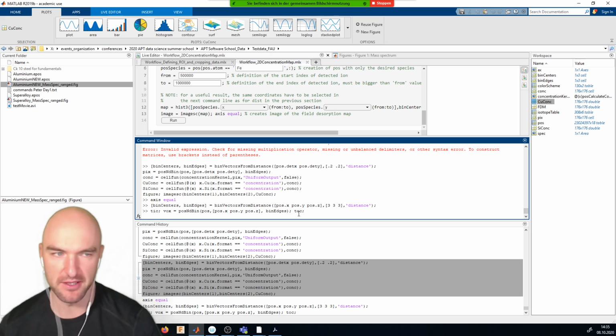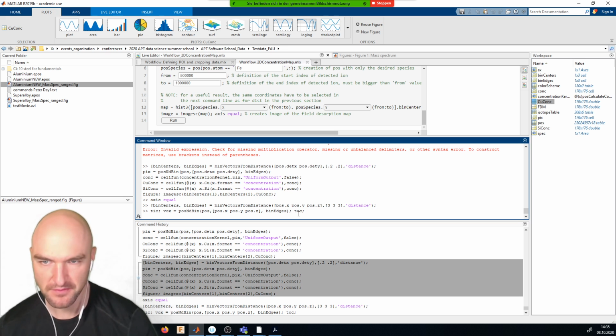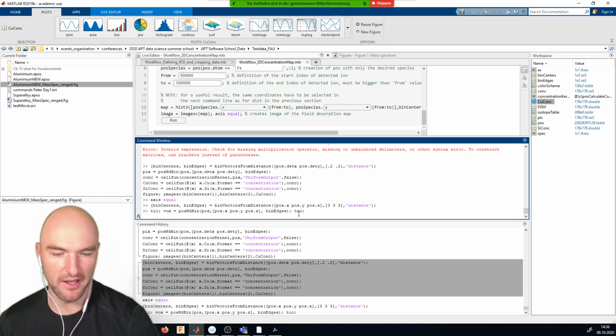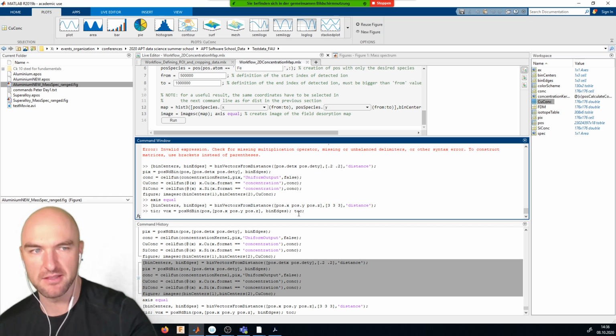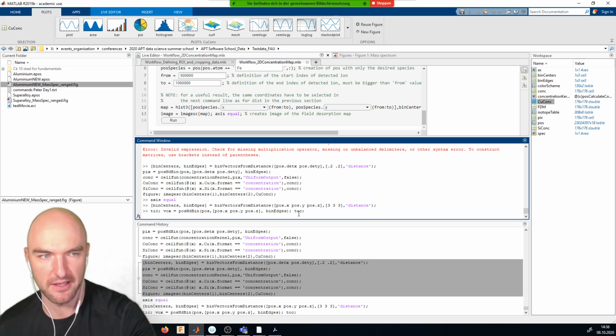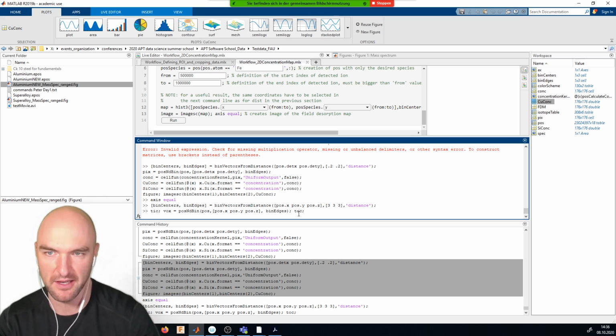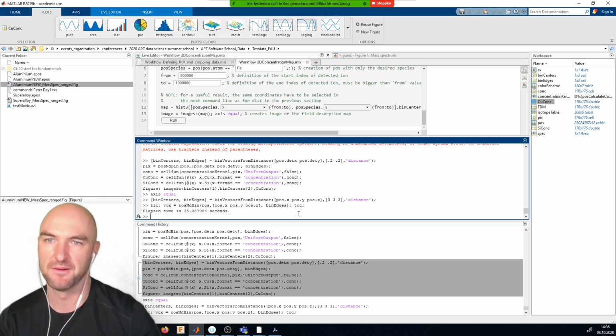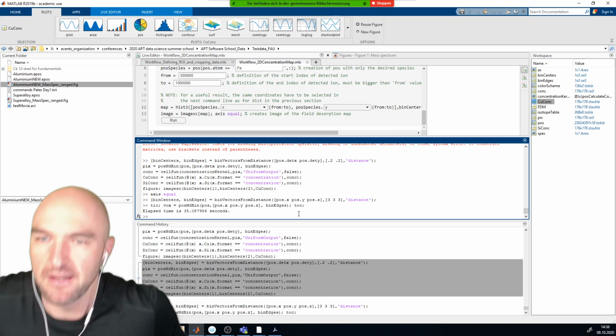Silicon and nitrogen, for example, right? If you would take silicon 29 and silicon 30 as the basis for calculating the silicon content and subtracting them from the rest in the peak at 14 for the nitrogen, then